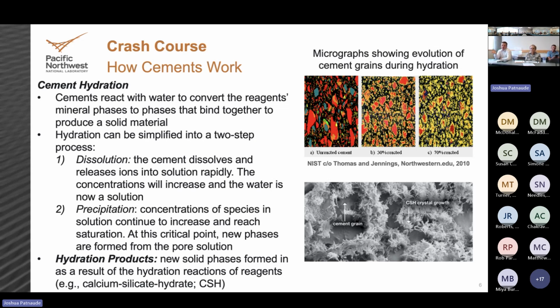Those are materials that were designed just to last for a few decades, but based on the knowledge they had at the time. But those materials, because of that continual environmental reactions, have actually become stronger and less porous over time because you get those unreacted grains that slowly continue to react. The hydration products themselves, they'll slowly evolve. So if you're smart with your design, you can make materials that are very long lasting and maintain the properties that you've engineered into it.